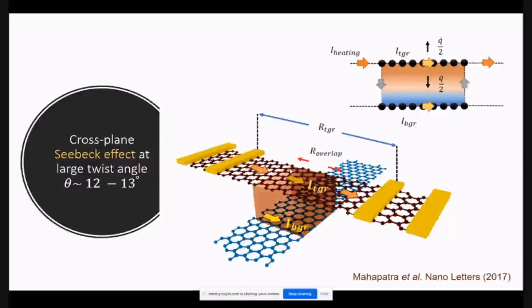I don't know whether it's possible. So we have this upper layer, and we pass current in this, which is called a heating current, and we measure the voltage between the upper layer and lower layer. Okay. So it's essentially a thermoelectric potential. Okay. So using a heating current, you heat up one layer with respect to the other and measure the voltage across the two layers, across the van der Waals gap.